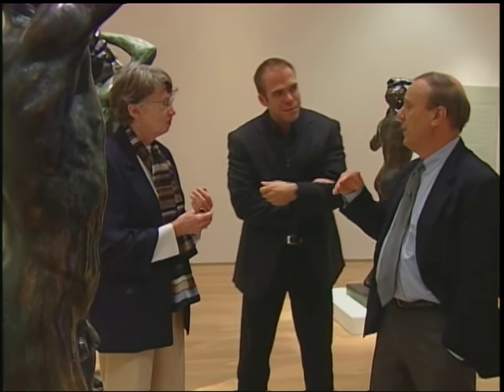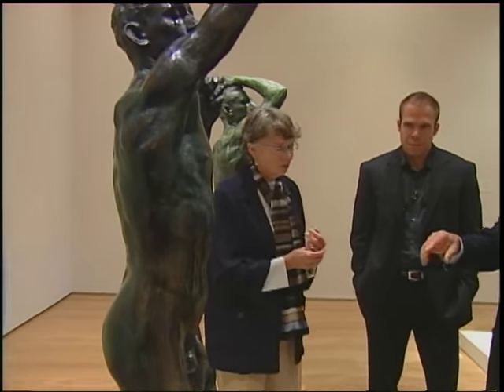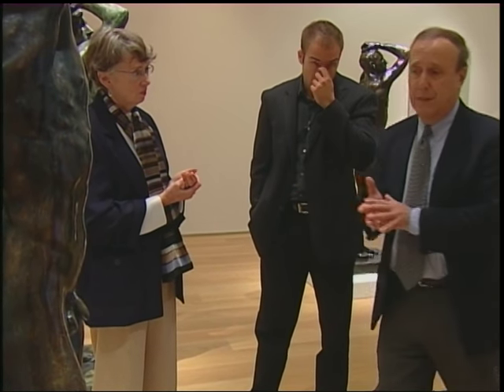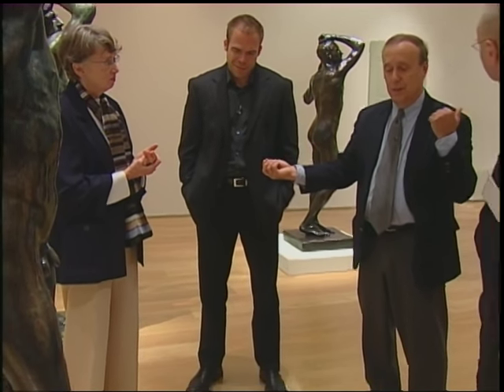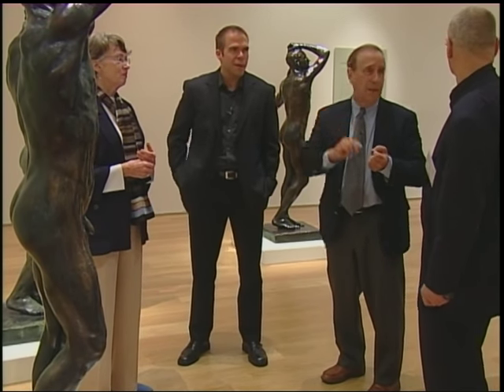Well, I'm going to say too, from having done quite a series of X-ray diffraction and other analyses of older patinas that we've made, that even the patina that looks stable and visually is the same from a crystallographic point of view, depending on the chemistry of the patina, it will actually change even at room temperature, protected, in the period of 5 years, in the period of 10 years. Depends on the chemistry of the patination. Right. They are not stable. They're not made of stable chemicals. They alter subtly, and the analysis that you make 10 years ago will not be the same as the analysis you make now for quite a few patinas that are applied at Rodin's shop.